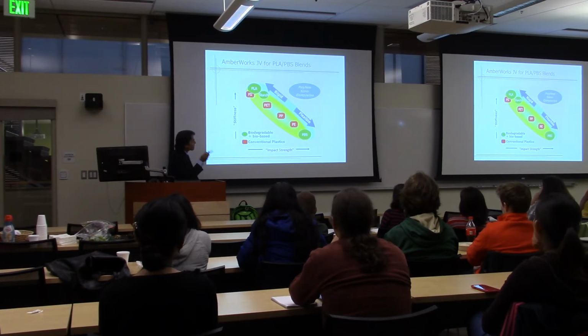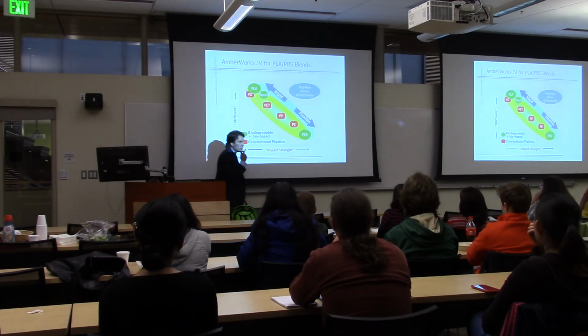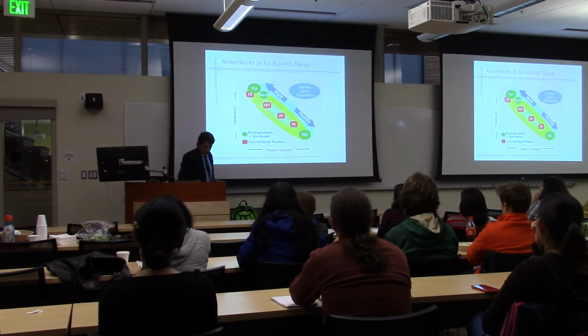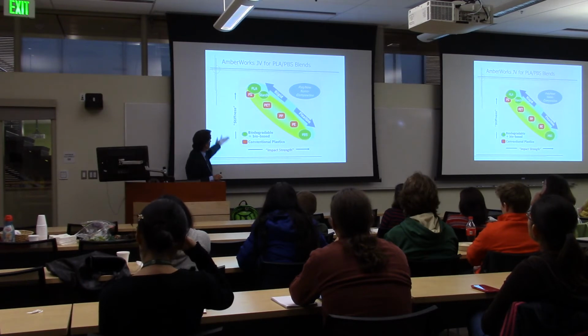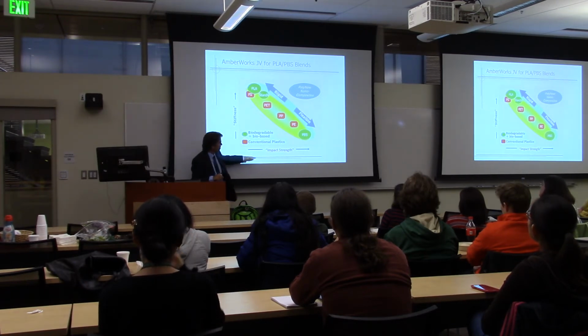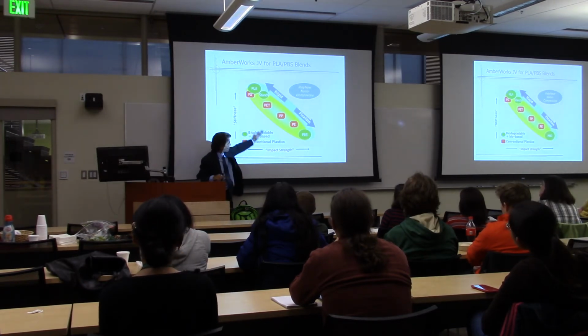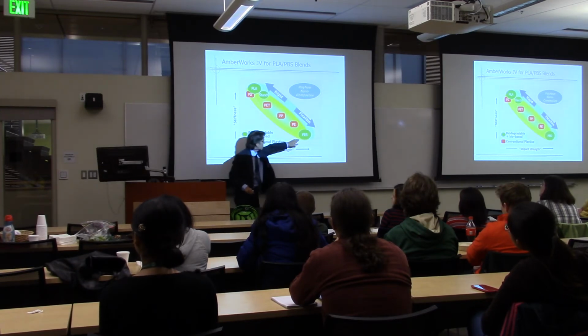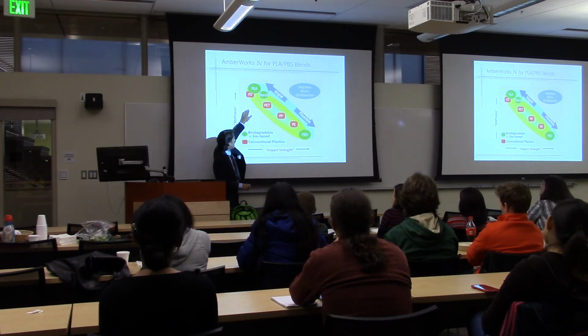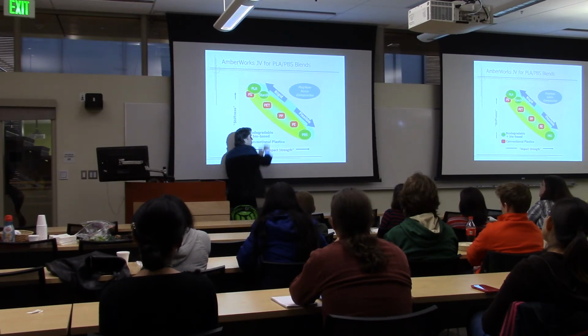So I mentioned Bioamber and the fact that they're making PBS, and that makes a very nice material to blend with PLA. In fact, if you think in terms of stiffness versus impact strength, you can get all kinds of different properties depending on the relative amount of PBS versus PLA. But that's a typical trade-off curve. And so what we'd like to do is move in that direction.